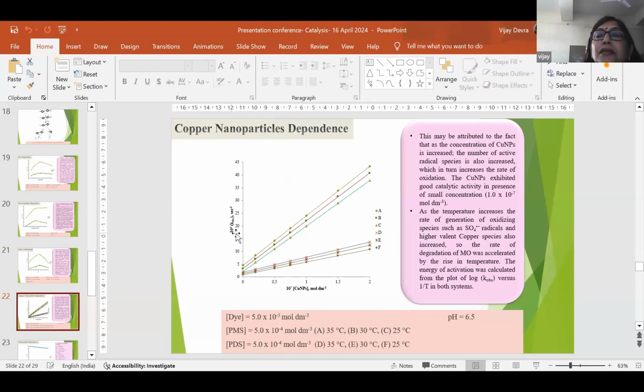And this is where we see the effect of copper nanoparticles on the degradation of methyl orange. As we increase the concentration of the copper nanoparticles, the rate of degradation of methyl orange increases, because more active sites are available as the copper nanoparticle concentration increases.